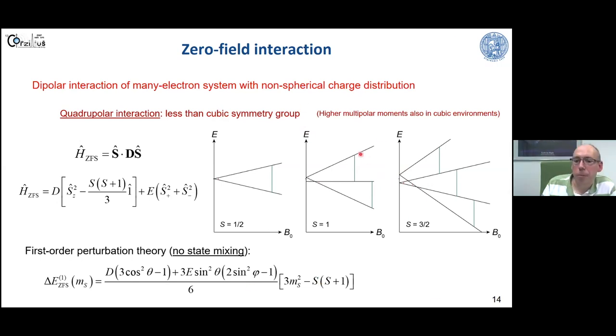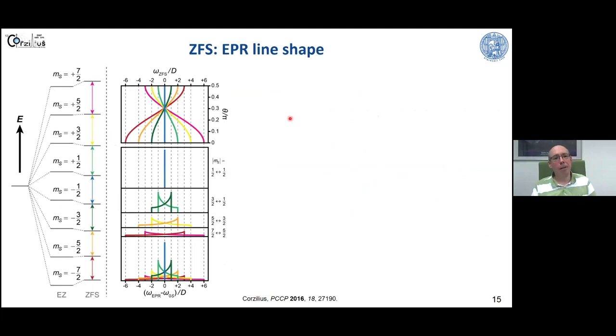But very quickly, we also have to distinguish between half integer states and integer states. In half integer states, we always have a doublet with an M_S minus 1/2 and an M_S plus 1/2 state, which is connected by an allowed transition. In so-called non-Kramers systems, we don't have this, and this means we always have a shift of all the transitions due to zero field interactions, whereas this one is not shifted at all. So we always have one resonance, which is at the center of our Zeeman interaction. And this becomes apparent much better here in this diagram, where we see at zero, without any angular dependence, our central transition, which is exactly this transition between the central Kramers doublet, between M_S minus 1/2 and M_S plus 1/2.